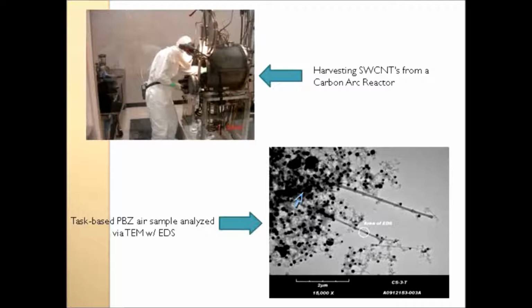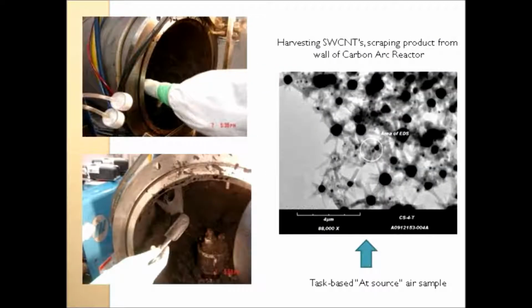Again, here is an example of my at-source sample, as close as I could get to the opening of that reactor, trying to see if there's a plume that comes out. Can I capture it? Well, yes, I did capture it. You can see here he's scraping the inside to continue harvesting the material. And here's what we get on the TEM. Again, there are these fibrous structures, but mostly it's catalyst and some soot. So you can get an idea that not everything is going to come out as single fibers. In a perfect world, that's what they would want. But these are the initial products that are harvested. They are subsequently handled by different treatments to clean them up and produce their final product, which is a single-wall tube.